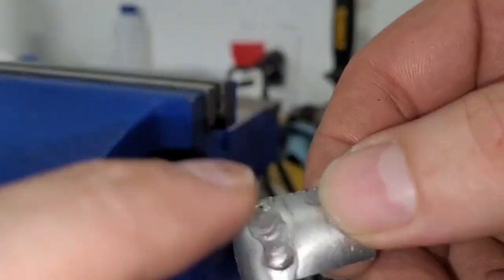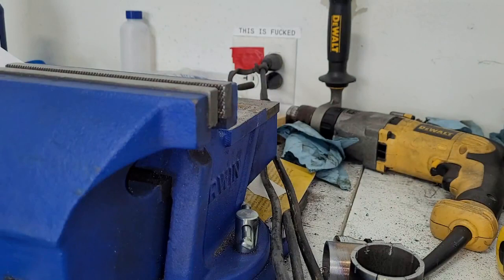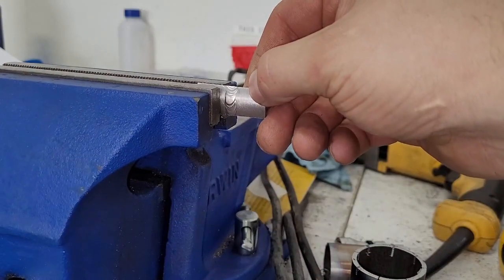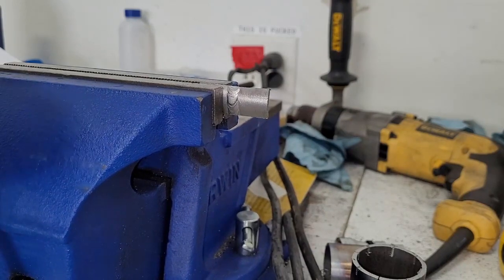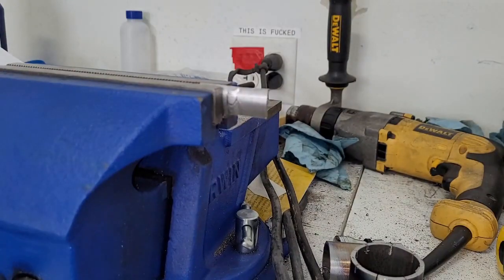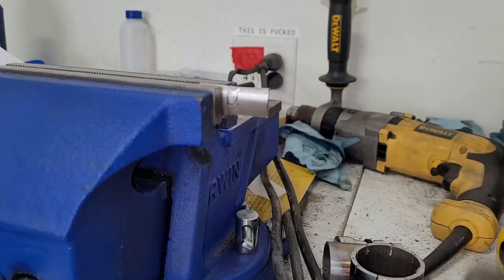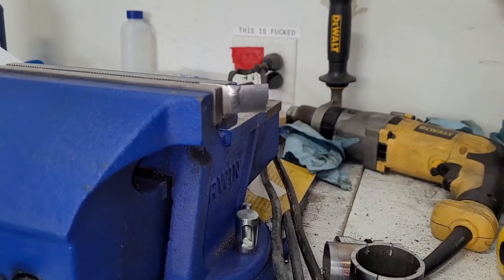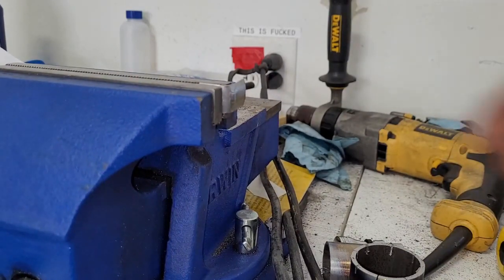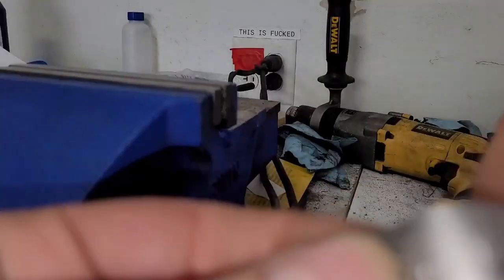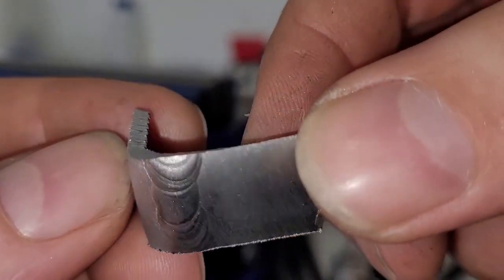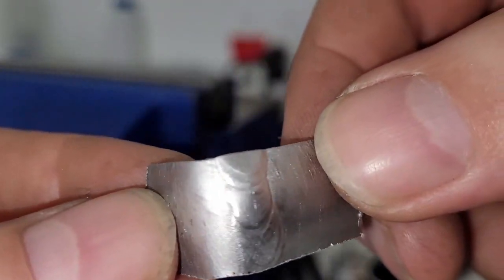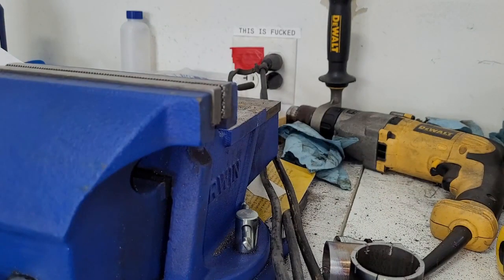Like I said, I think all these are going to do fine when you put the weld in tension. This is the last sample that we're going to do that. These are probably all going to crack when we do it the other way, since these didn't have as good a penetration to the other side. But that's why we test, to find out. If it turns out my assumption about this weld is wrong, then it's good that we tested, because then we find out. I'd rather be mistaken and then corrected. I don't see anything. Okay, so all four welds in tension on both welds have passed.